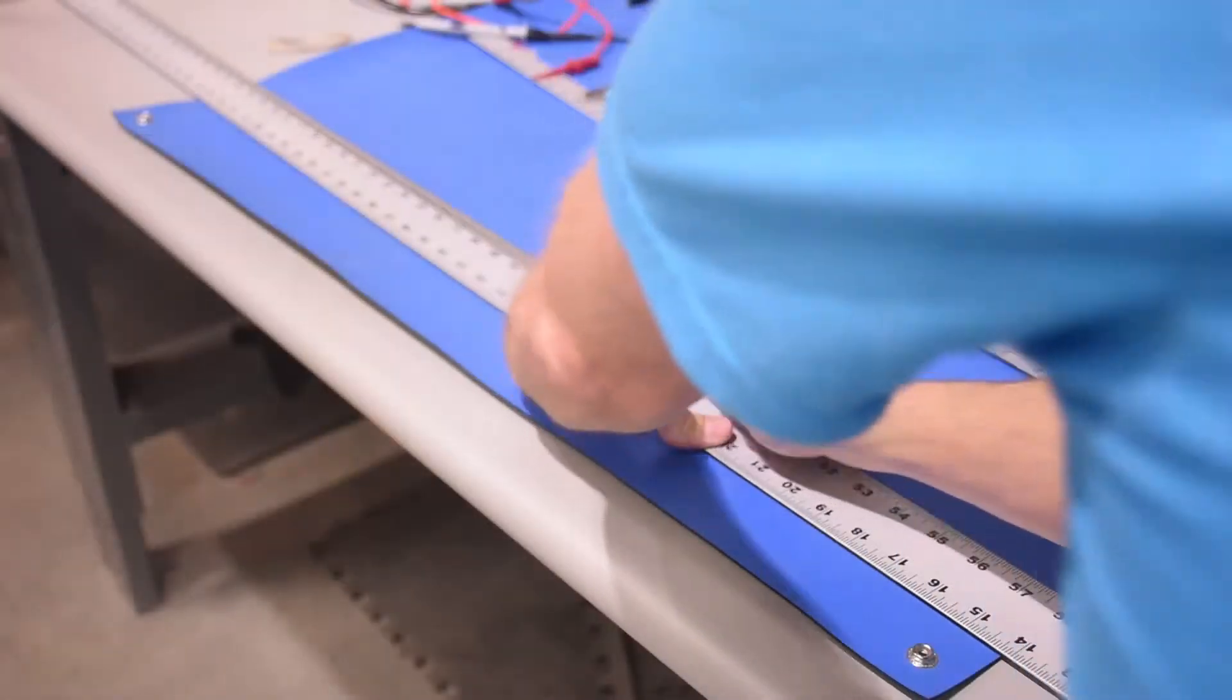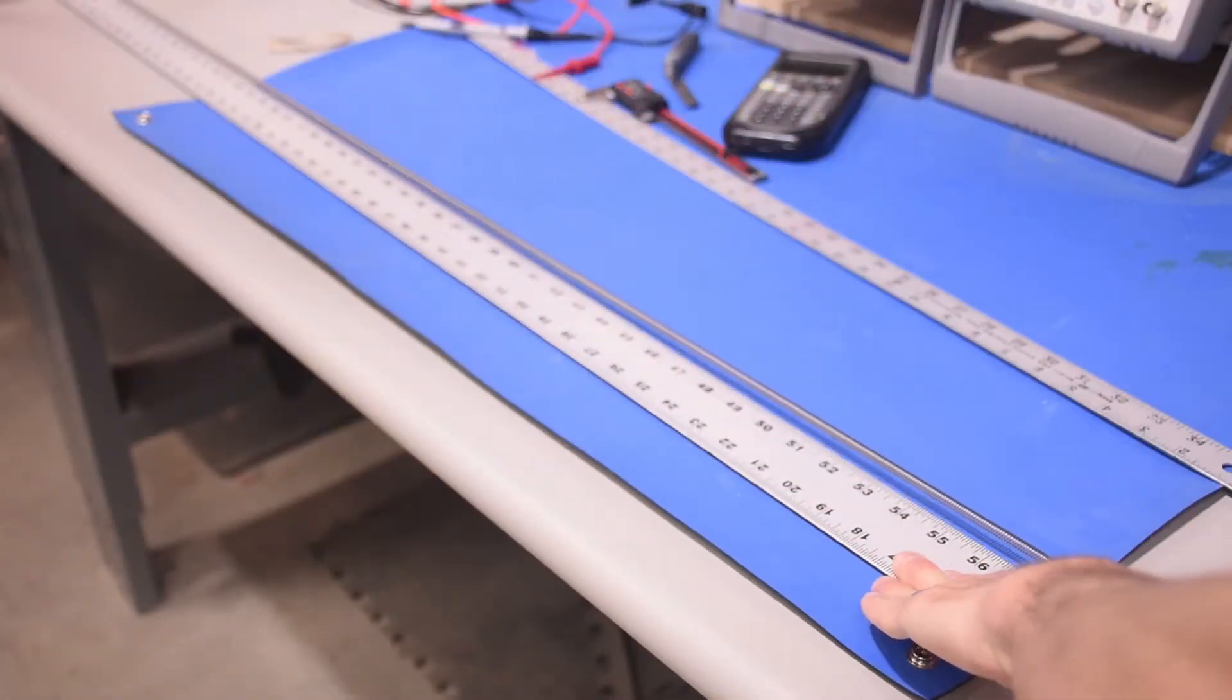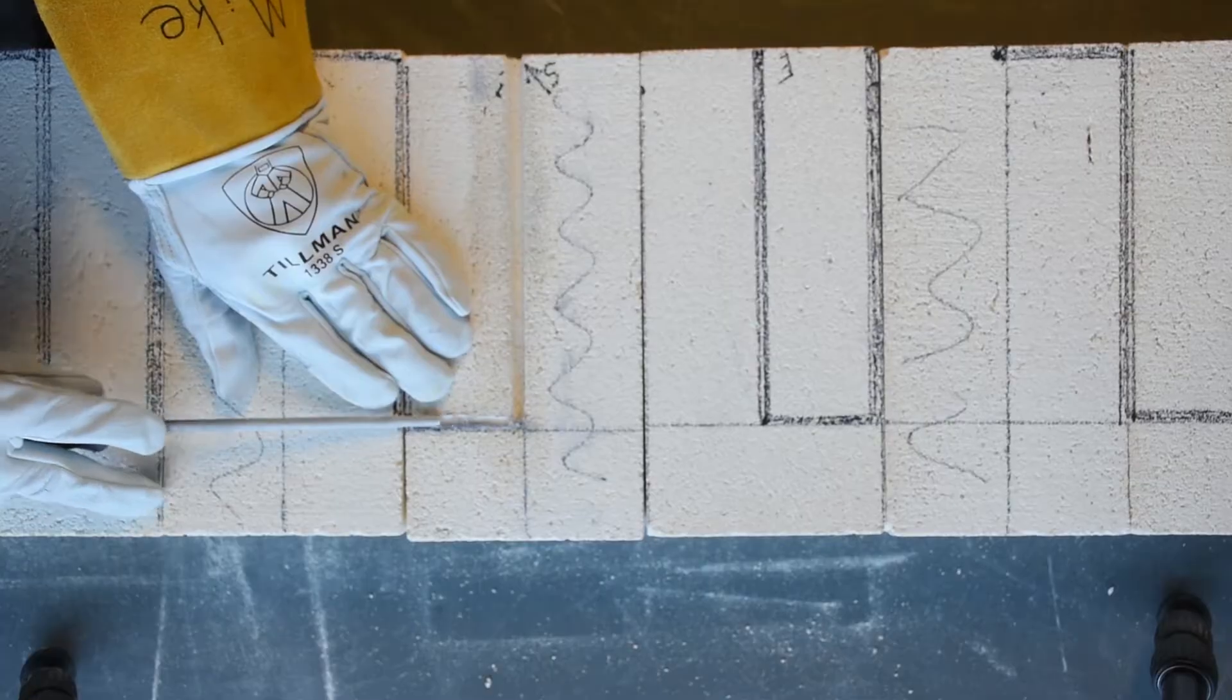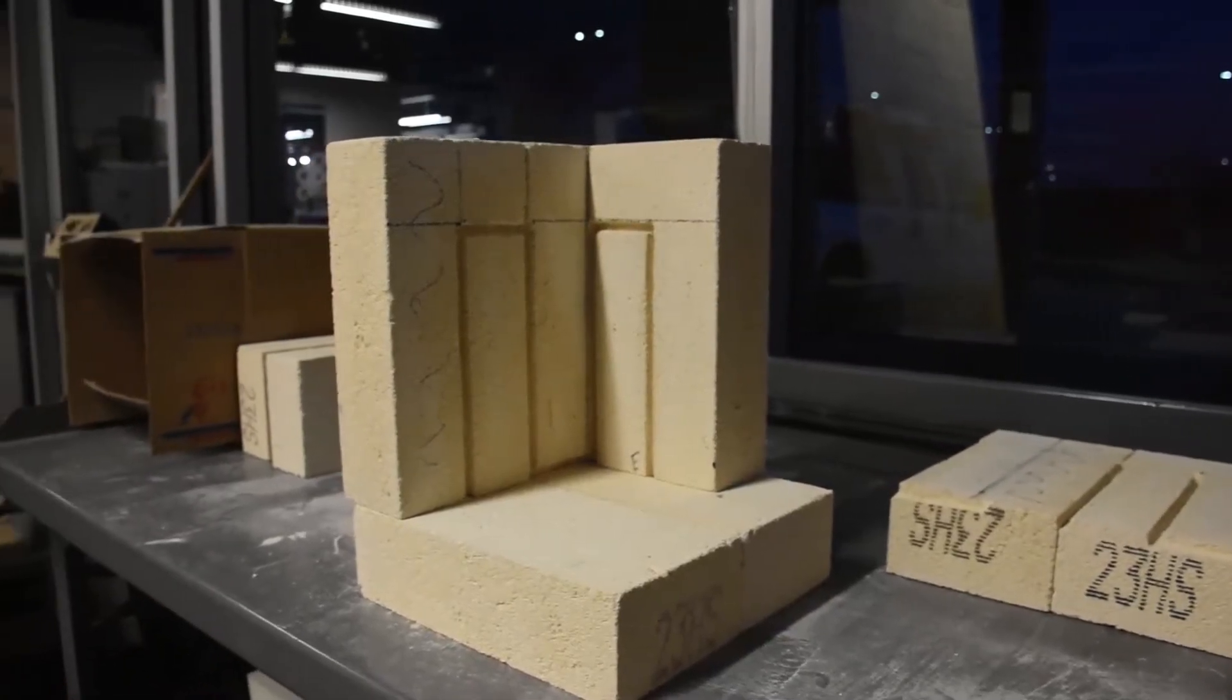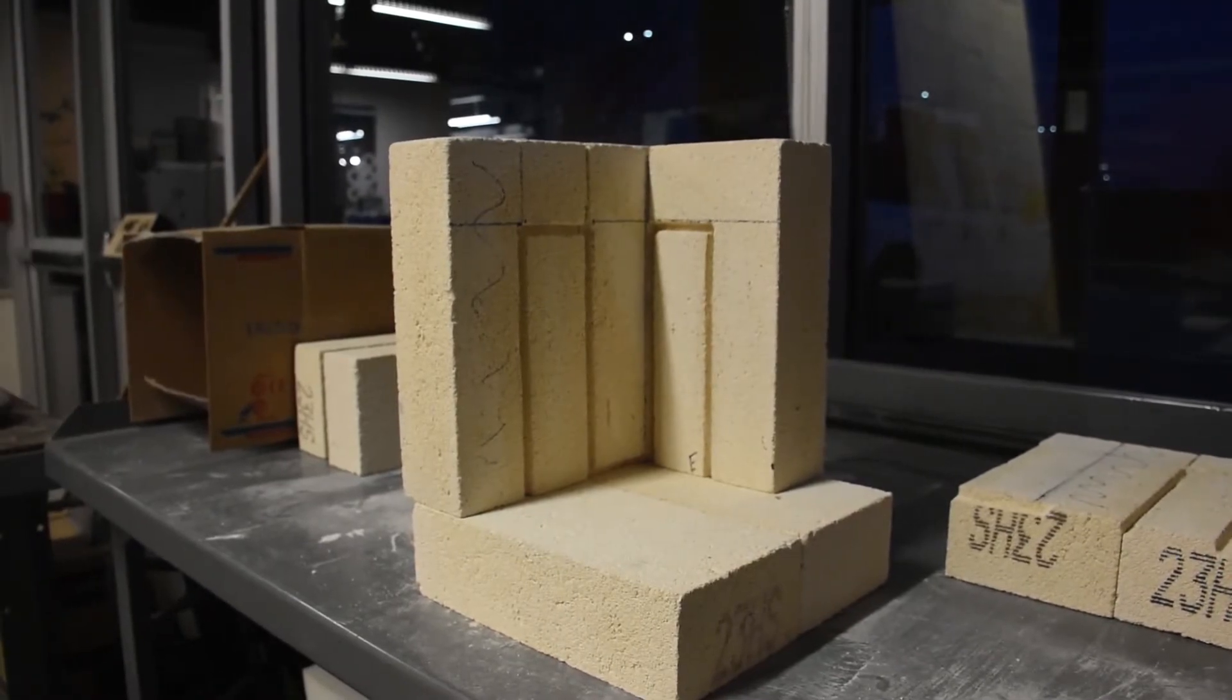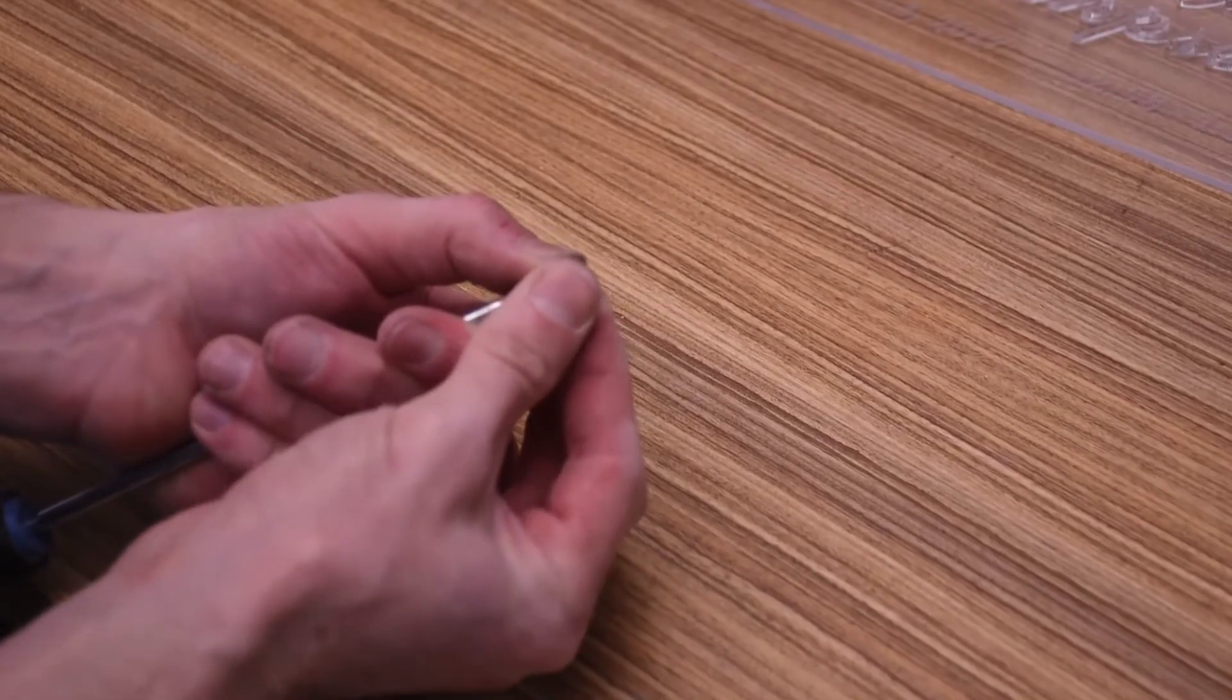The new version has a single coil which I stretched to 70 inches and then ran in vertical grooves. The grooves were easily carved with a circular file and no grinder was needed like with the Acme Firebrick. The coils still fell out once they stretched so I bent some steel staples and pressed them into the slots and they finally stay in place.